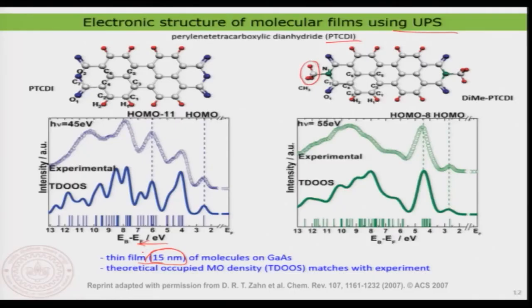You can see clearly that this is the binding energy. The binding energy is increasing, and somewhere here I have the Fermi level. But clearly in the experiment, for some region, about 2 eV, there is no density of state, or no electrons coming out of the material, because it is a semiconducting organic molecule which has a clear HOMO-LUMO gap. Because of that, you have this flat, no density near the Fermi energy. As you go deeper in energy, you start to get the first peak, and that corresponds to the HOMO of the molecule. That is also something we discussed in the case of scanning tunneling spectroscopy as well.